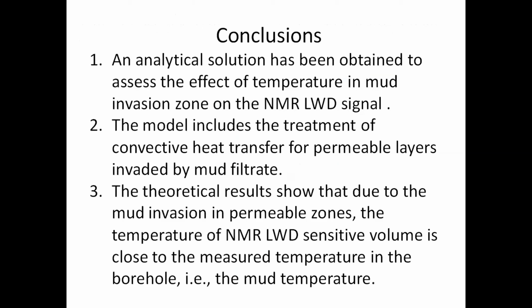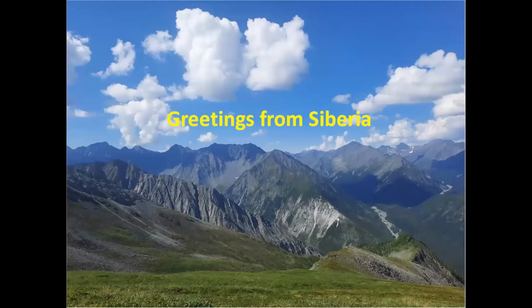Conclusions. An analytical solution has been obtained to assess the effect of temperature in the mud invasion zone on the NMR logging while drilling signal. The model includes the treatment of convective heat transfer for permeable layers invaded by mud filtrate. The theoretical results show that due to the mud invasion into the permeable zone, the temperature of the NMR logging while drilling sensitive volume is close to the measured temperature in the borehole, or the mud temperature. Thank you very much, and greetings from Siberia.